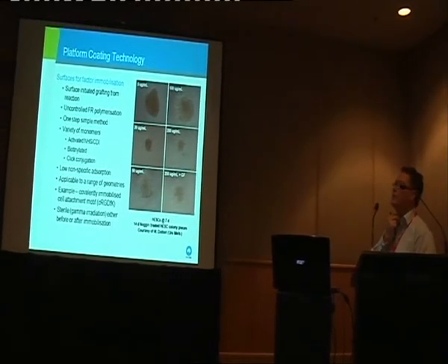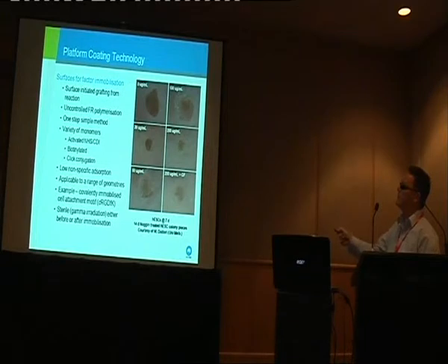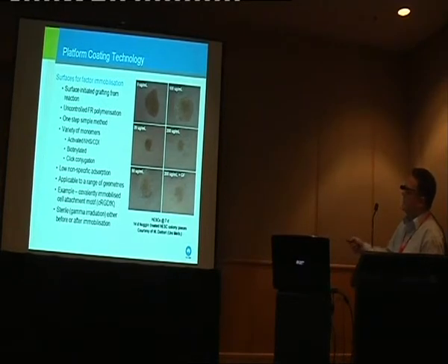We've also applied the same sort of surface to embryonic stem cell derived neural progenitors. So this is a neurosphere, as I showed you earlier, that basically forms in a low attachment plate. If you increase the amount of peptide that you have on the surface, the cells start attaching onto the surface in a dose-dependent fashion, and they start spreading out away from the initial attaching neurosphere. And when you add an appropriate growth factor, in this case basic FGF, the cells start proliferating out and differentiating down the glial lineage.